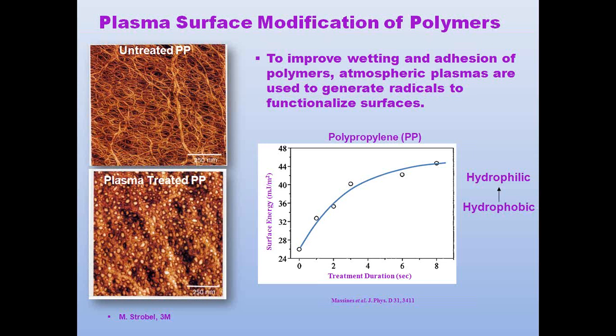You can see in the left margin an untreated polypropylene structure under SEM, and then you can also see a plasma-treated polypropylene structure. And what you're seeing at that surface are small nodules. These are, again, small, low molecular weight nodules that make their appearance most typically with plasma treatments, usually flame plasma treatments at the surface. And of course, if you were to overtreat a polypropylene or any other type of material, they would increase in number, and ultimately you would lose contact with the native surface of the material, and that would allow you to create a delamination effect, which you certainly want to avoid. So understanding the power density requirement and the functionalizing requirement of the surface is key to a successful outcome.